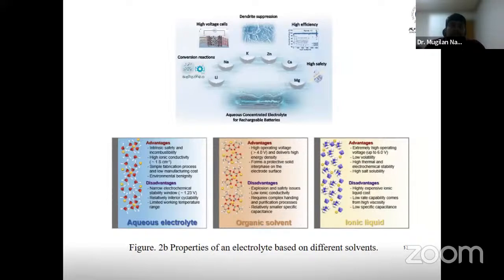The only drawback is that it has a narrow electrochemical stability window, relatively inferior capacity, and a limited working temperature range. Whereas in organic solvent, it can go beyond 4 volts, and it is highly protective to the solid interface of ions and transportation of electrolytes. The major disadvantage is that it has explosion and safety issues, and it may not have good conductivity. And in ionic liquid, extremely high voltage can be reached, with low volatility, high thermal and electrochemical stability, and high salt solubility.